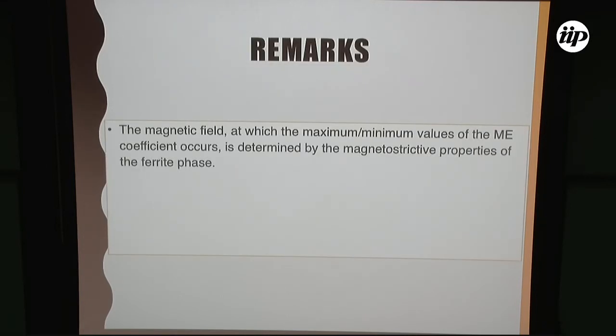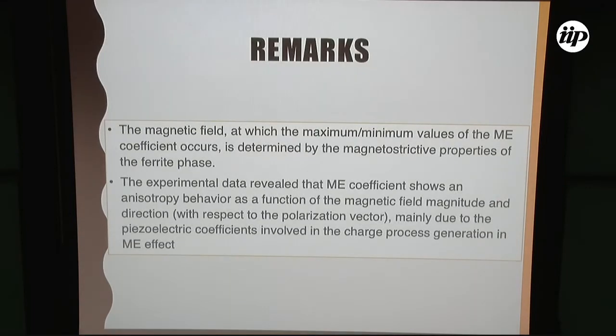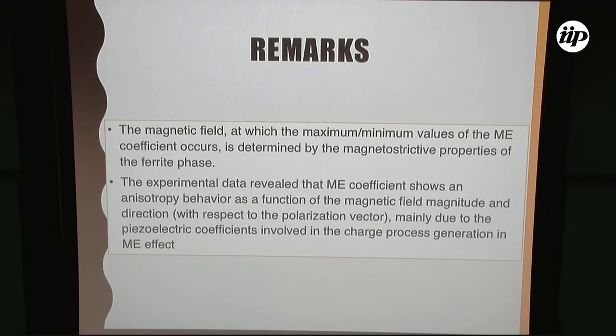The magnetic fields at which the maximum and minimum values of the magnetoelectric effect occur are associated with the magnetostrictive property of the ferrite phase. This dependence of the magnetoelectric coefficient shows an anisotropic behavior as a function of the applied magnetic field and its direction with respect to the polarization vector. Okay, this connection of the magnetostriction and the piezoelectric effect is very important to understand the next step of our study,